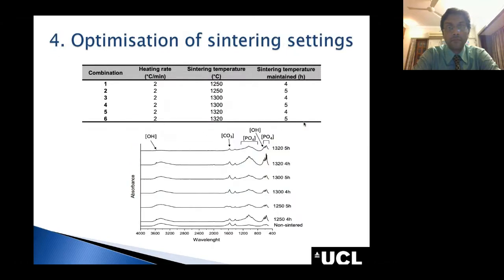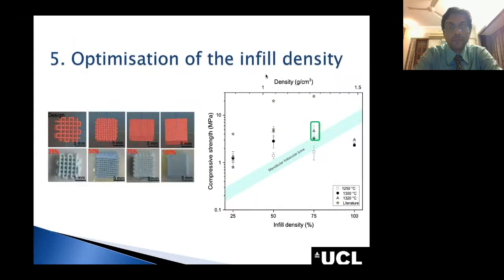As we are working with hydroxyapatite, we know that to increase its mechanical properties, a sintering step can be added. We tried different combinations of sintering temperature and time maintained in hours, and you can see from the FTIR graph that any of those temperatures allow the hydroxyapatite to remain in its phase. Therefore, we decided to choose the highest sintering temperature.